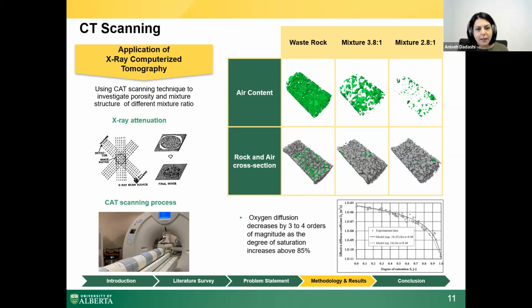We wanted to see how tailings fill the void spaces because oxygen diffusion is very limited as saturation goes above 85%, and it can reduce the acid generation potential. Also, for geotechnical stability, we know that the shear strength is higher if rock particles stay in contact.